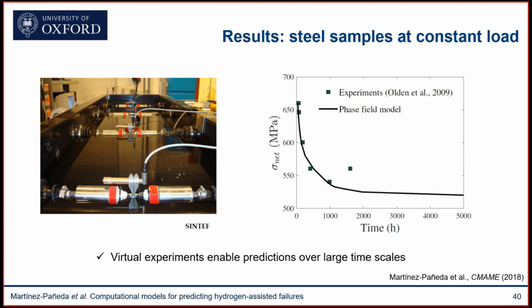So here they have duplex stainless steels that were immersed in a seawater bath. They contain a notch, and they were subjected to a constant remote stress. And then the time to failure was measured. You can see here that the symbols are the experimental data points, and you can see that all of the samples fail relatively early for engineering standards.